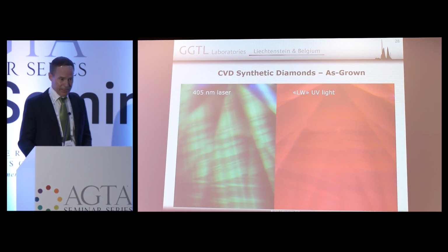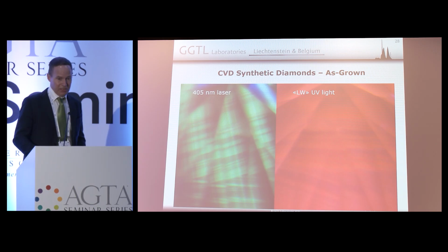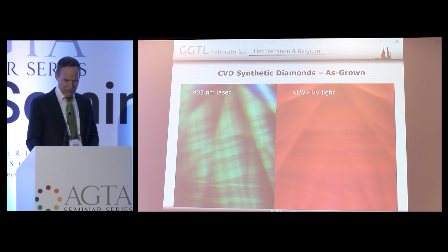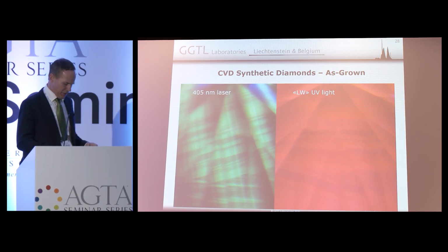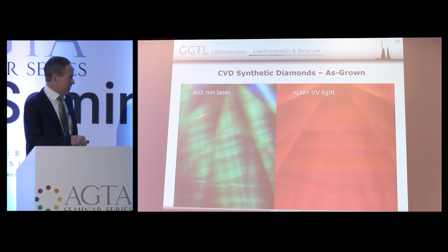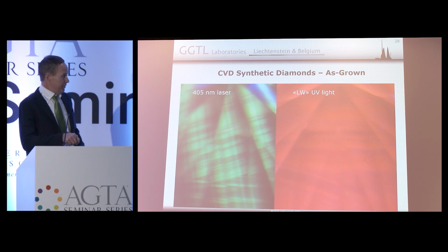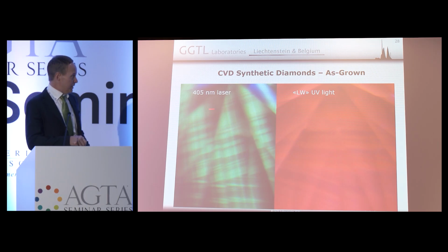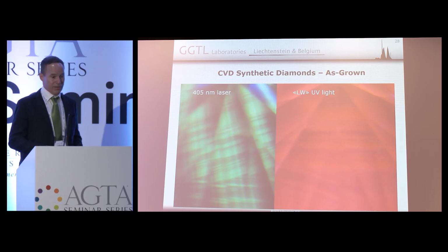Let's have a look at some CVD synthetics. So CVD synthetics compared to HPHT, completely different process of growth. So this is a layer by layer growth on a seed crystal, and you can see the layer by layer growth here, okay? You see the layers, you see them here as well. This is long wave UV for the same stone, and this is 405 laser for the same stone.